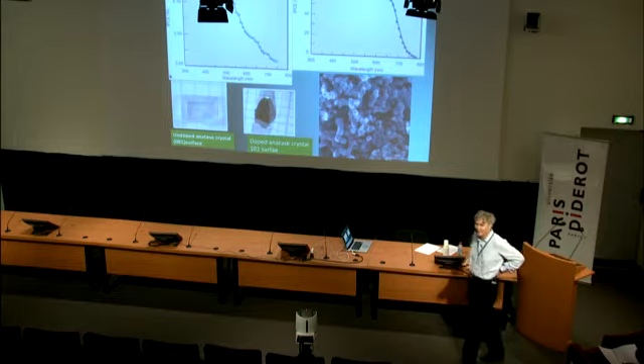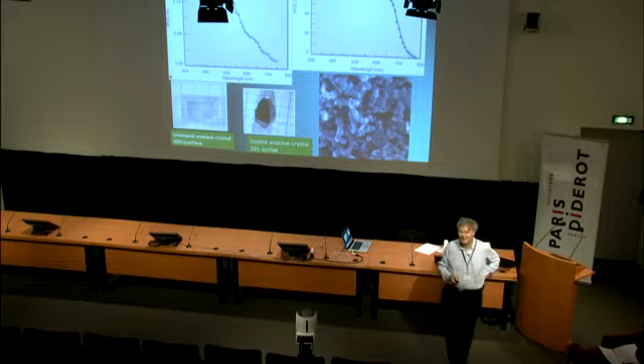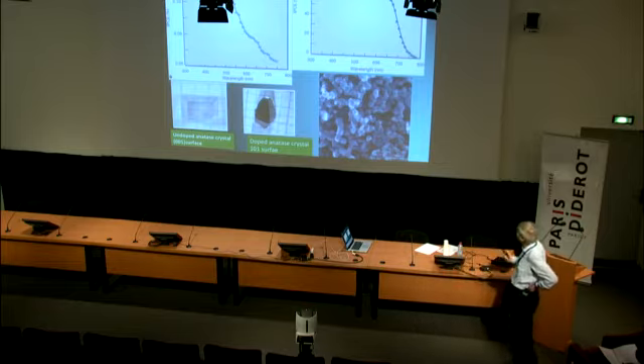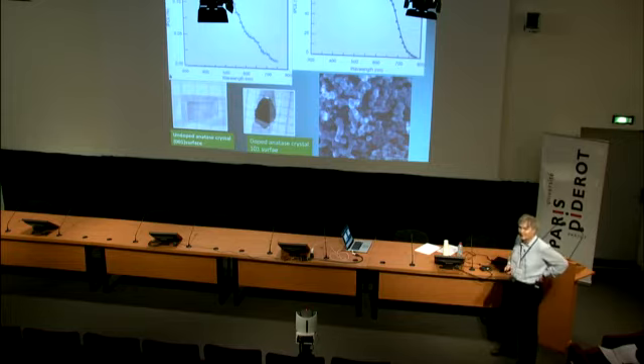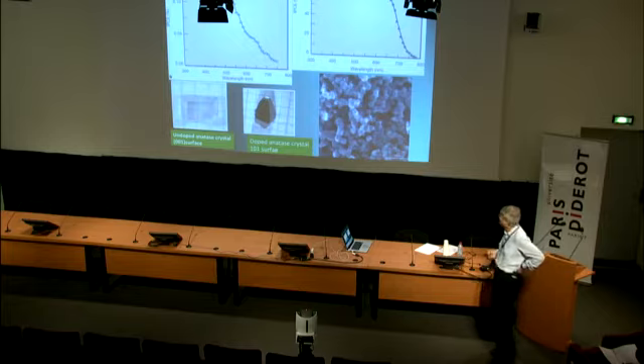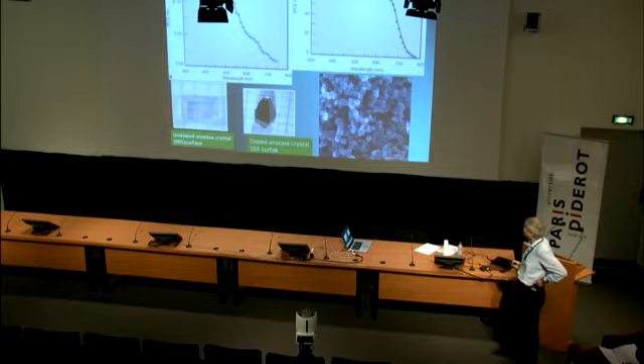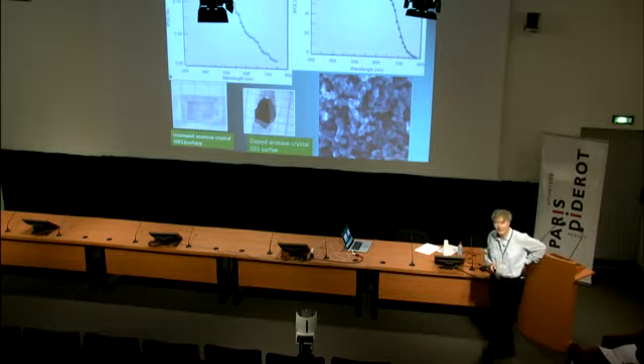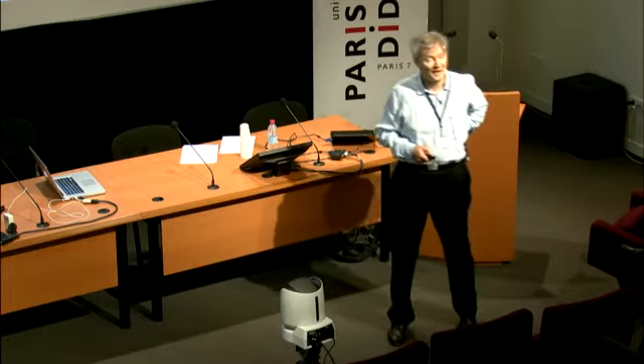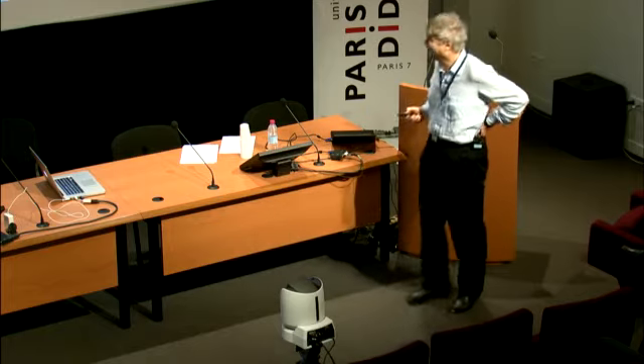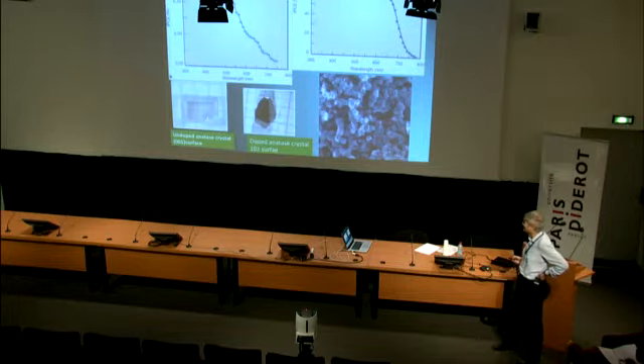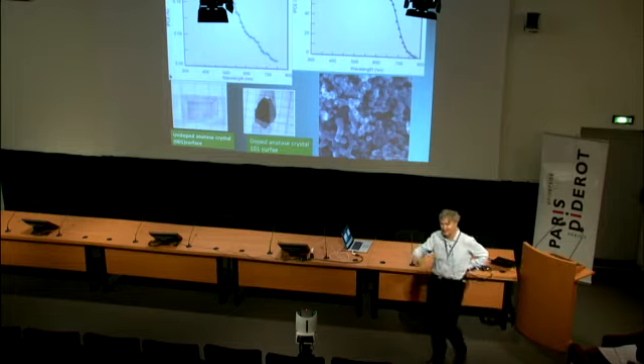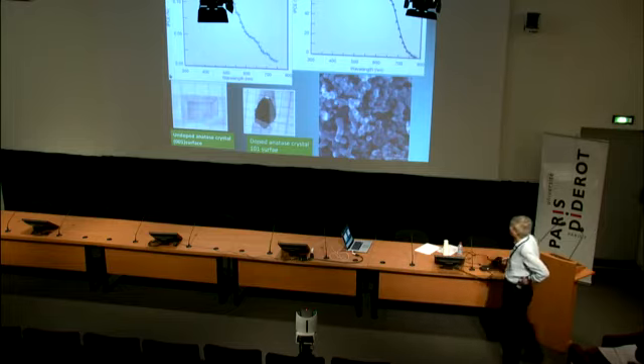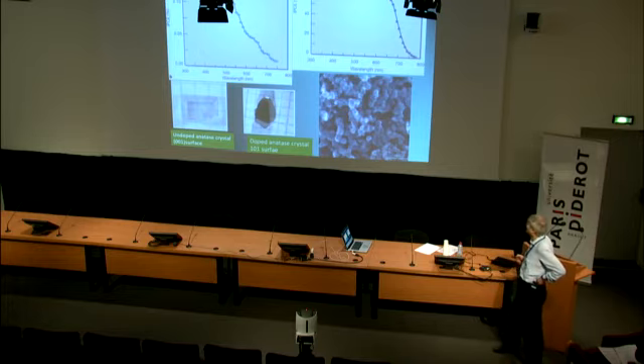That's, of course, nothing to brag about if you're going against technologies, the solid-state cells that have over 80%. But you can get over 80% when you use those nanocrystalline films. So the breakthrough in this technology was to go from the single crystal to the nanocrystals. And the nanocrystals are, of course, much cheaper. This film costs about 1 Swiss franc, maybe even less. But scientifically, it was entirely justified to make those single crystals. We can cut them at different angles and see the faceting, how it affects the performance. So for fundamental research, this is a very important discovery.